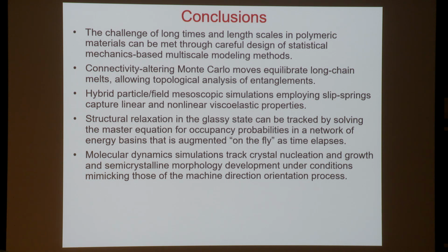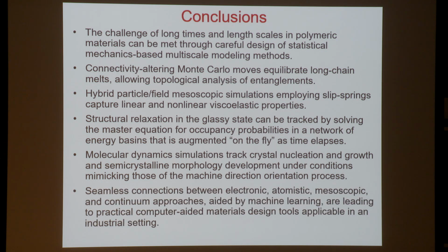And for ordered systems, for systems which crystallize, one can try to perform non-equilibrium molecular dynamics to see how the morphology of these systems can evolve at given conditions of deformation rate, epsilon dot, and temperature, and see how the semicrystalline morphology develops. That would be very important for permeation and mechanical properties. Finally, I would say that seamless connections between the electronic, atomistic, mesoscopic, and continuum approaches, nowadays aided by machine learning, are leading to practical computer-aided materials design tools which are applicable in an industrial setting.